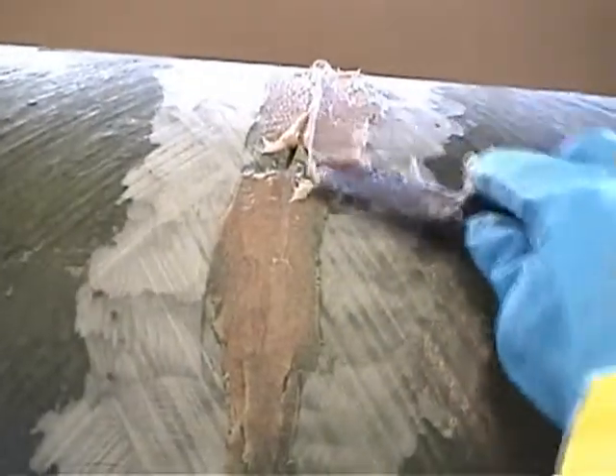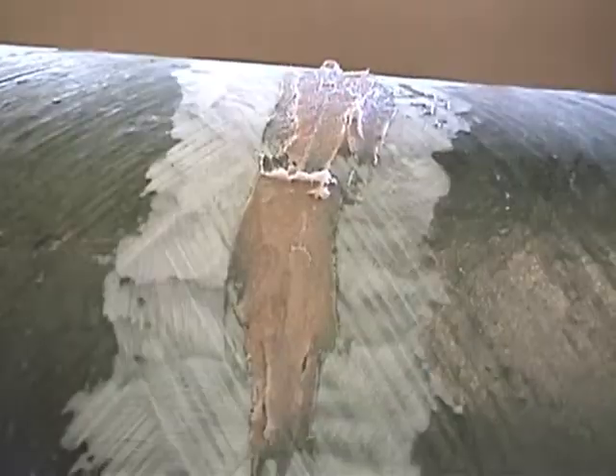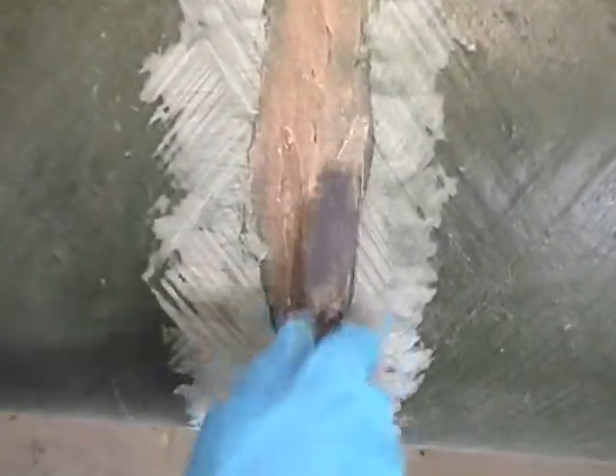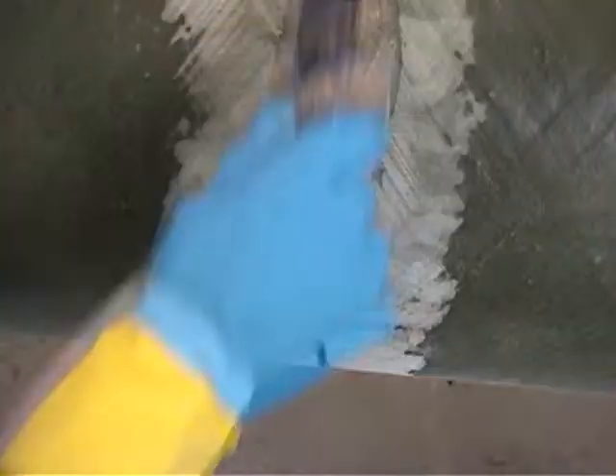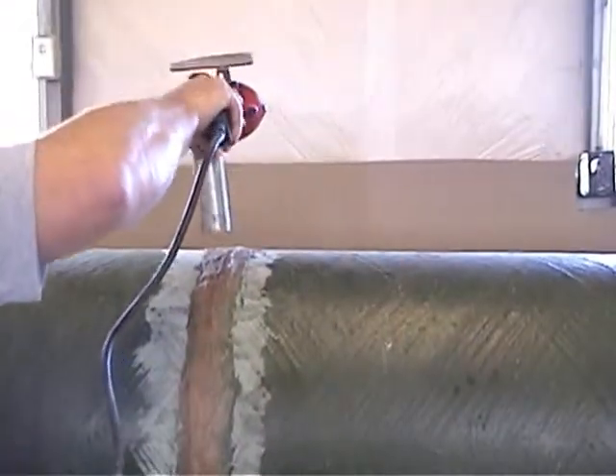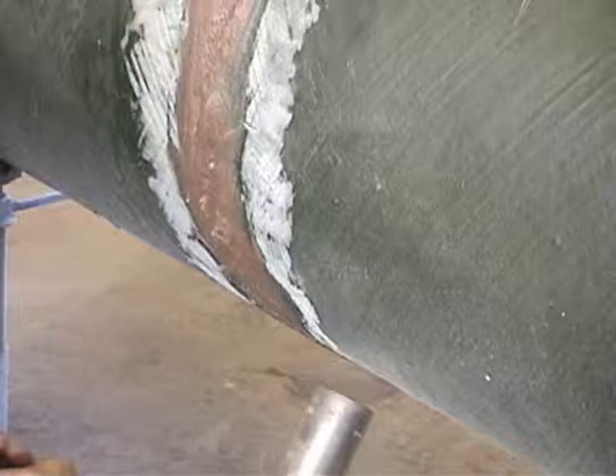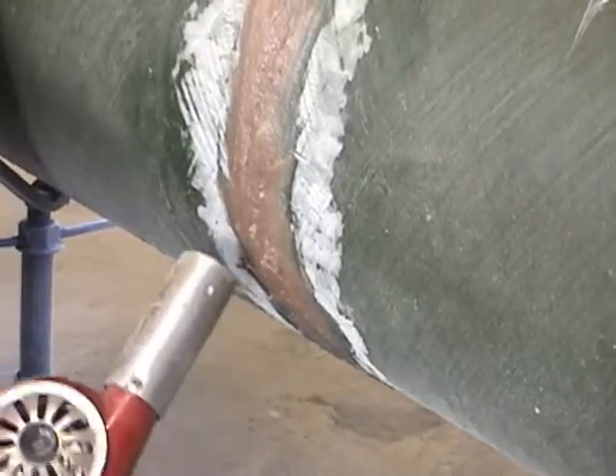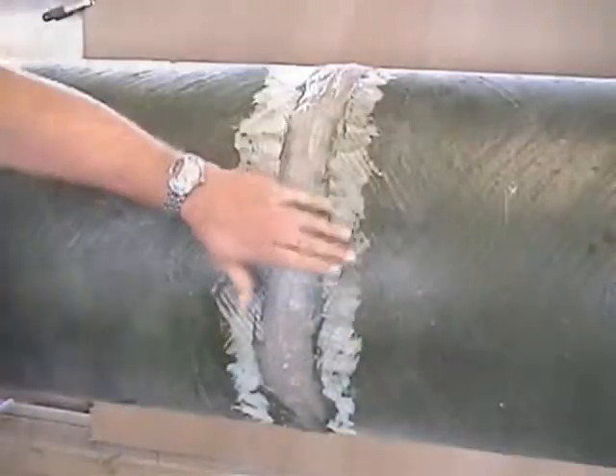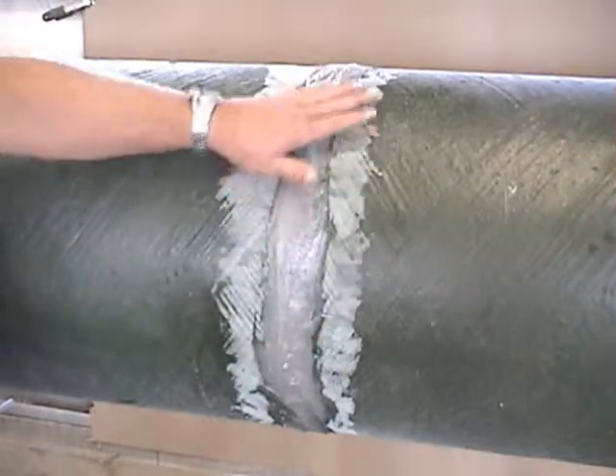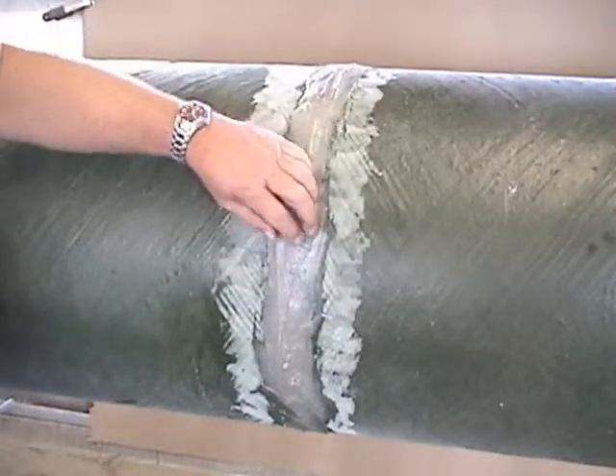What the adhesive does is fill any gaps that you may have between the pipe ends. Apply about 1/8 to 1/4 of an inch over the seam all the way around the pipe. The adhesive is temperature sensitive, so the cooler it is, the longer it takes to cure, and the hotter it is, the shorter time it takes. So using a heat gun, we will accelerate the curing process. It should only take about 15 to 20 minutes to cure with a heat gun to make it ready to grind. Now that the adhesive is cured, you need to let it cool down before you start grinding.